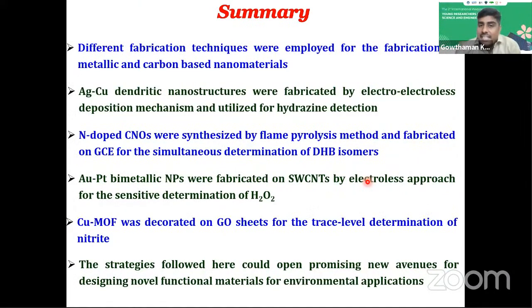Different fabrication techniques were employed for the fabrication of metallic and carbon-based nanomaterials. Ag-Cu dendritic nanostructures were fabricated by electroless deposition and utilized for hydrazine detection. N-doped carbon nano onions were synthesized by flame pyrolysis and fabricated on GCE for DHB isomers. Au-Pt bimetallic nanoparticles were fabricated on SWCNTs for H2O2 determination. Copper MOF was decorated on GO sheets for the trace level determination of nitrite. Surely the strategies followed here could open promising new avenues for designing novel functional materials for environmental applications.